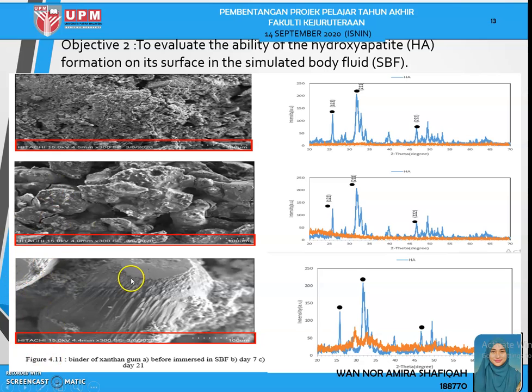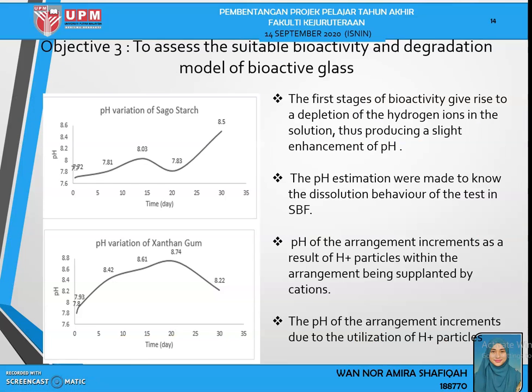After 21 days, this picture shows that the surface has more cracks, and the characteristics of hydroxyapatite are observed. So for the XRD analysis, it clearly shows here that after 21 days, the peak is higher compared to the 7 days. So when the time increases, the hydroxyapatite formation also increases.